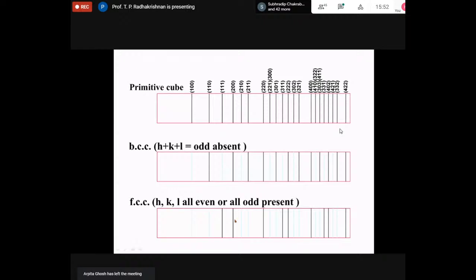And if you look at these numbers carefully, these conditions are present. H, K, and L are all even or all odd. All three are odd here, all are even here. Here it is two even and one odd, so it is missing, and so on and so forth. Similarly, in another case, if it is a BCC lattice, you will see the condition that the sum of H, K, and L should be even. If it is odd, it will be missing.